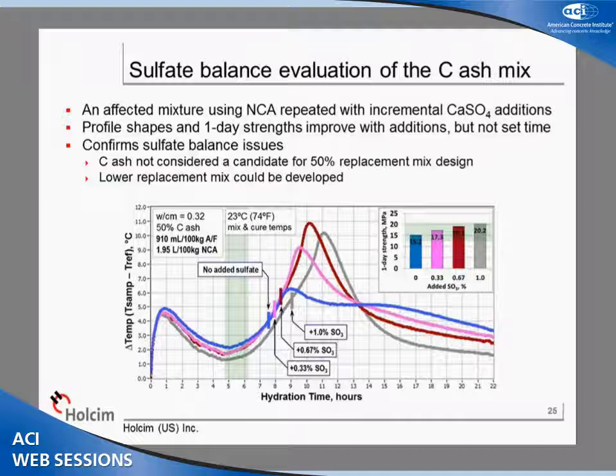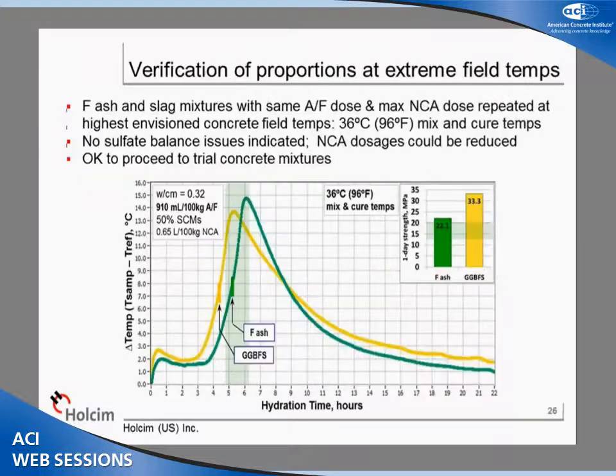Now, you can't do this in concrete. You don't want to try that. So what we've got is a situation where we can now rule out the Class C fly ash if we need to go to a 50% replacement level in this mixture. You might be able to use 40%. You'd have to start over and try that again.